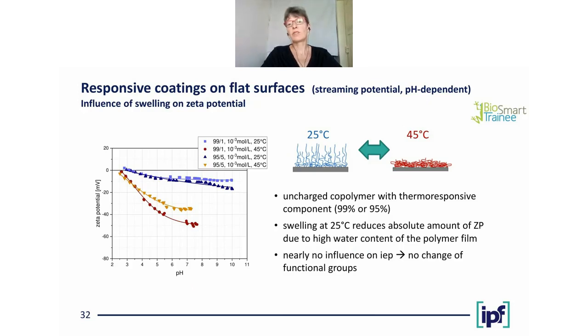We also use thermoresponsive brushes that are swollen, for instance, in this case, at low temperatures and are collapsed at higher temperatures. We don't see a pronounced change of the isoelectric point in this case in the Zeta potential, but we see a decrease of the Zeta potential at low temperature as a result of the swelling. As I explained, if you have more water in the brush, then the potential difference between the brush and the surrounding solutions becomes smaller.